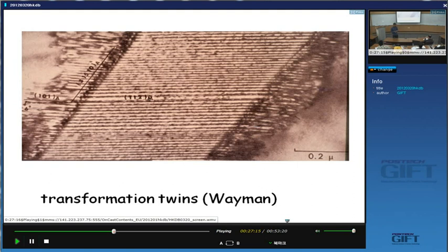So when martensite forms extremely rapidly, the interface is much more mobile when we have twinning. Okay? So martensite that forms extremely rapidly will be twinned, and martensite which has a dislocated interface and you produce the slip steps will tend to be slipped martensite.